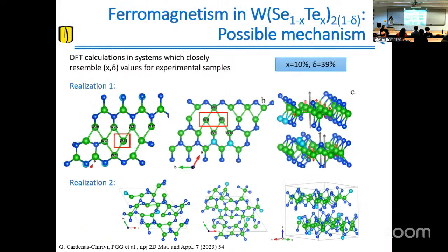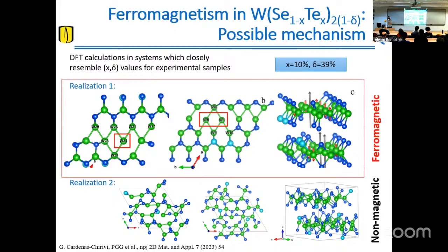How can we explain that? If we have defects in the system, vacancies of the chalcogen atoms, the tungsten ions are not surrounded by many chalcogens. This promotes the localization of the d electrons in this tungsten, creating magnetic moments. And we have actually confirmed this through DFT models. So this tungsten over here, in which the arrow represents the amount of magnetism for that atom, and this one too, these two here. We have also simulated some realizations in which we do not have many tungsten ions surrounded by vacancies, and those realizations are not magnetic. So this actually speaks of the importance of vacancies in this system.